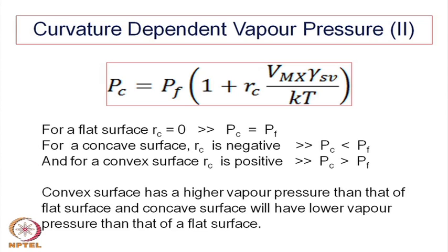If it is a spherical surface, it will be uniform everywhere, but when an agglomerate or conglomeration of particles is made, all the surfaces are not of similar curvature. They have different curvatures at different sites, somewhere positive, somewhere negative, and that makes the difference and creates the so-called local driving force.